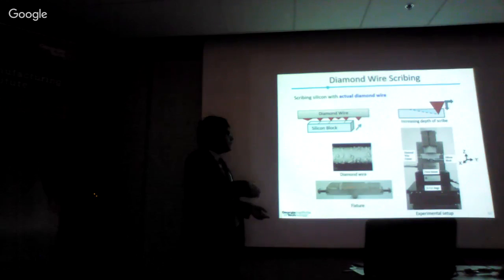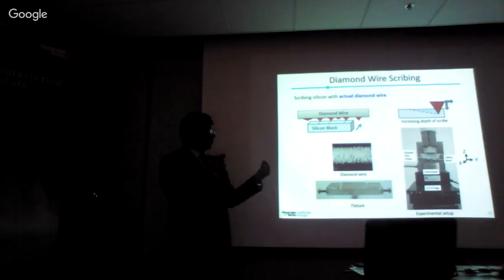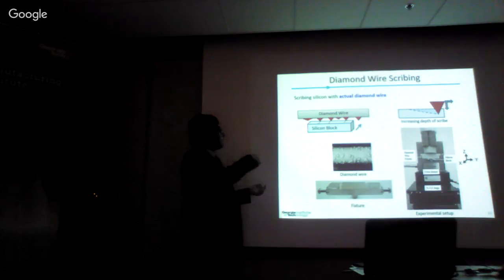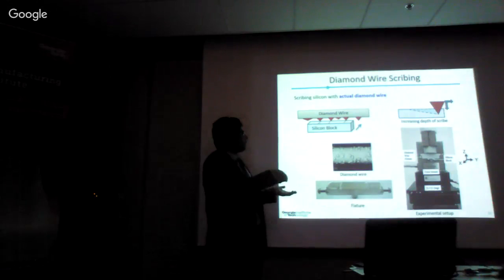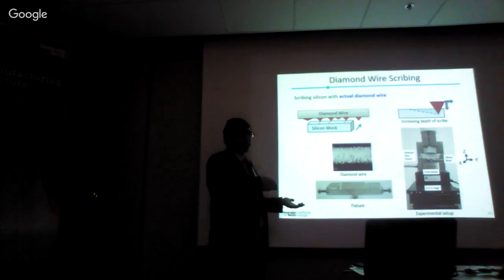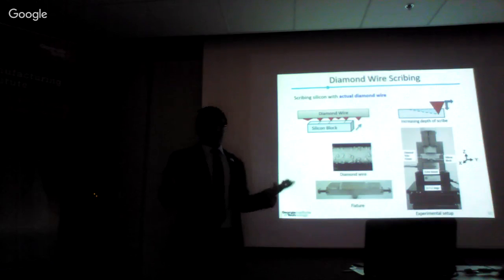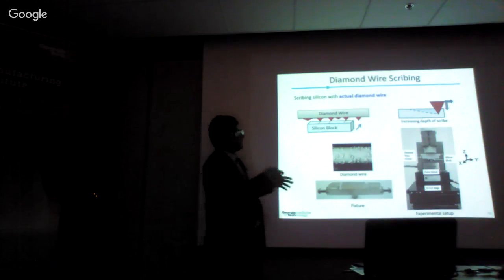There is a micro-milled groove here, which we cannot see in this image, which holds or supports the wire in place so that it doesn't move at all when we're scribing perpendicular to the wire. This fixture goes on this micro-milling setup, which is in our lab, where it is attached to this top attachment. The silicon block is below that, and the silicon block is put with a base plate on a force sensor, the Kistler microdyne, and then the force sensor is put on an XYZ stage, which is controlled by a computer, and I can scribe with increasing depth of cut.